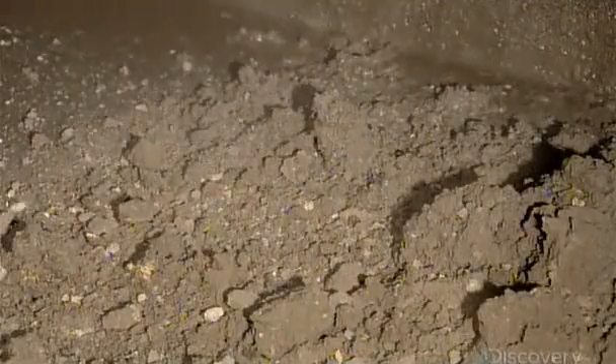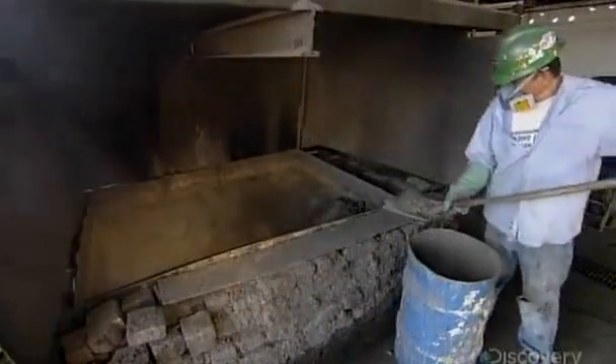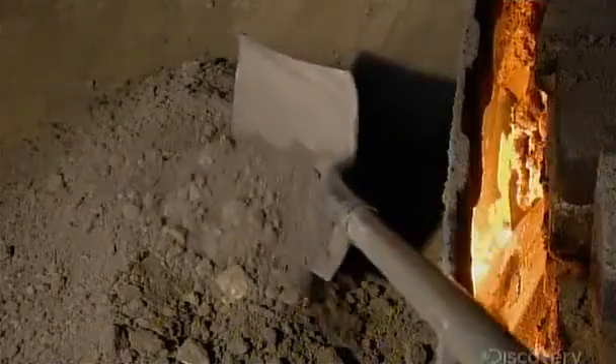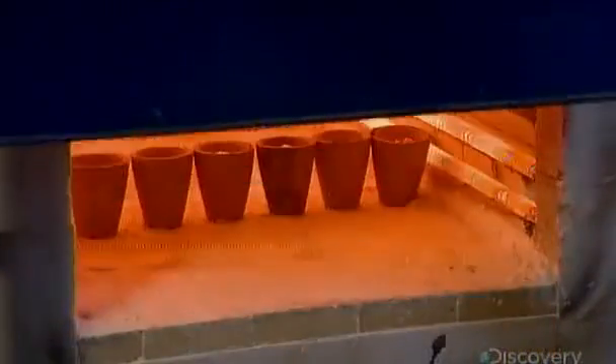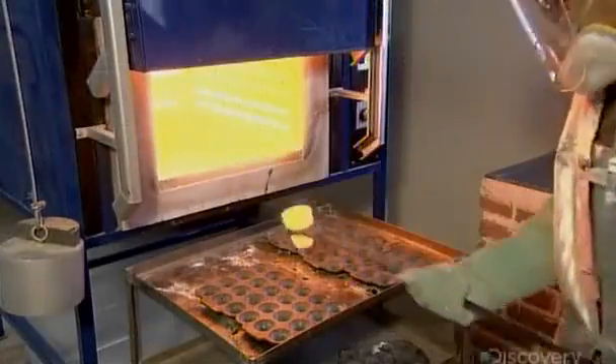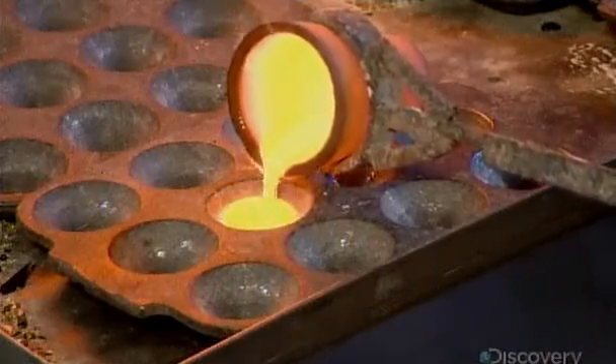This precipitate is composed of approximately 50% silver and 50% waste, the waste being a jumble of various metals, dirt, and other impurities. To separate the silver from the waste, they first dry the precipitate in a gas furnace for a couple of hours. In the mining company's lab, technicians continuously test ore samples to determine the grade, the term for the quantity of silver per kilogram of ore.